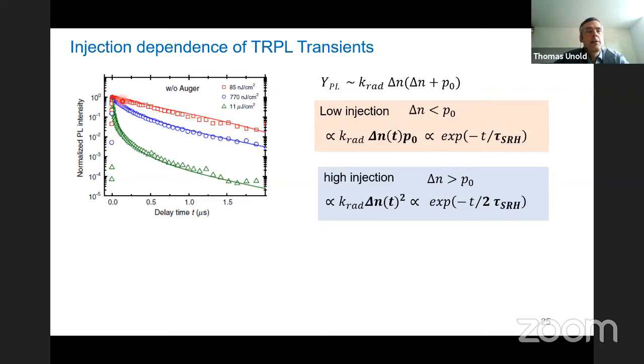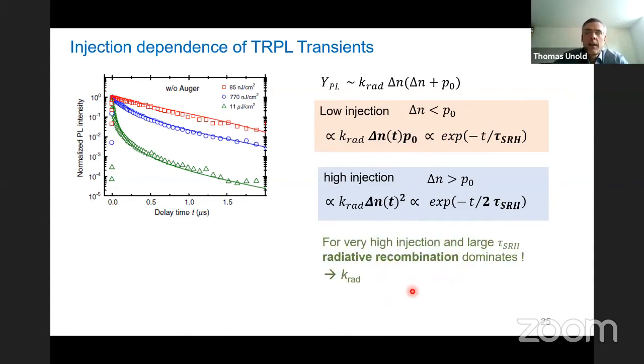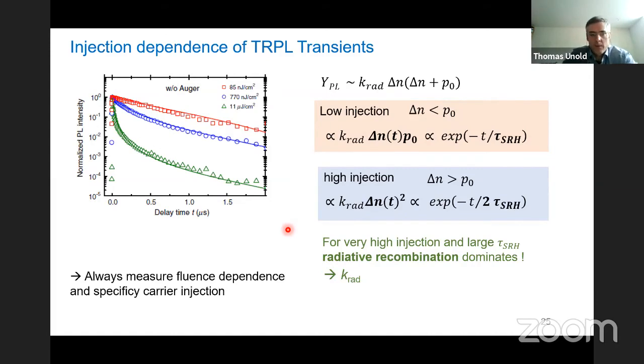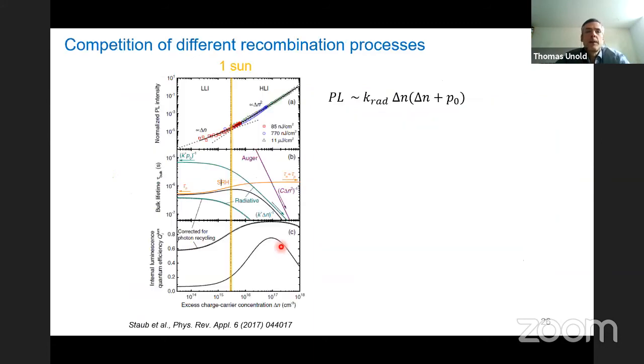If you go in high injection, still Shockley-Read-Hall non-radiative recombination, the recombination is faster because it's high injection. And if you go even higher injection, then the radiative recombination starts to dominate. And this is this case here. So you get a strongly non-exponential curve shape, which then allows you also to extract the radiative constant, which can be very useful in many regards. But what this already shows you is that it's always very good to measure the fluence dependence and to specify the carrier injection level at which you measure. Otherwise, it can be very difficult to interpret the data.